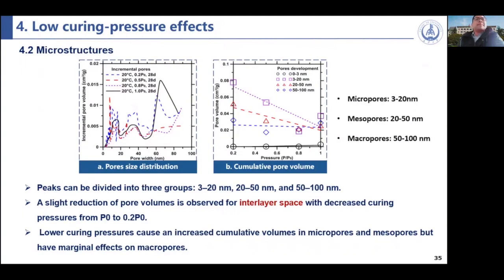We also calculate the microstructures, especially the pores in the cement paste. We can see the peak in this figure can be divided into 3 groups. The first one is about 3 to 20 nanometers, then 20 to 50 nanometers, and 50 to 100 nanometers. So we define the first group as the micropores, the second group as the mesopores, and the last group as the macropores. The micropores are always produced by the interlayer spaces.